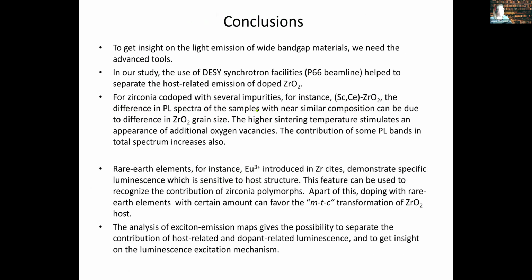So just to conclude my talk, first of all, I want to say that if we want to study wide bandgap materials, we need really advanced tools. For our luck, we were able to get access to synchrotron facilities. And this really, in my opinion, helped us to get some answers on the host-related emission in doped zirconium oxide. And what is interesting is that for doping with several impurities, we have different photoluminescence spectra for samples with similar composition. This can be due to either impurities which we do not control, or it can really be due to larger grain sizes or variation of grain sizes, and that will affect the presence or the nature of the host defects. And it's possible to use rare earth ions.